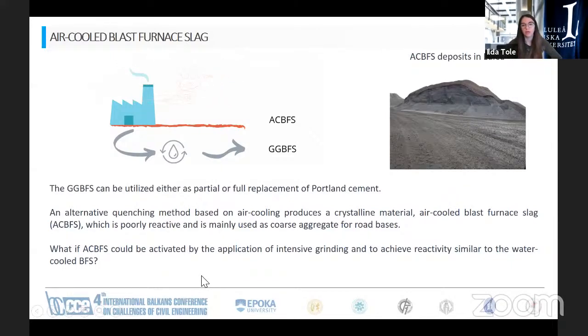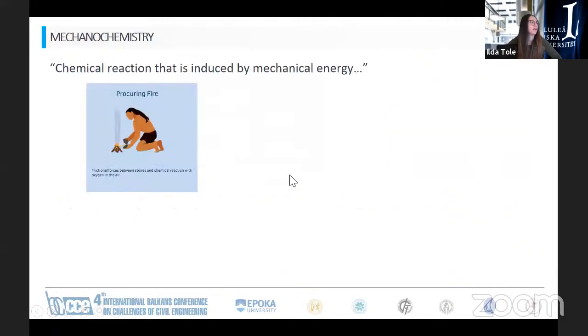Clay itself, but also air-cooled blast furnace slag, are usually thermally treated, and for clay, for instance, it is well known that calcination or thermal treatment can produce a material that is good as a replacement of cement. But again, the thermal treatment produces a lot more CO2 emissions because the temperatures to be utilized are quite high. So the proposal was to utilize another clean technology that does not use high temperature and does not use additional chemicals, and in this case it is mechanochemistry.